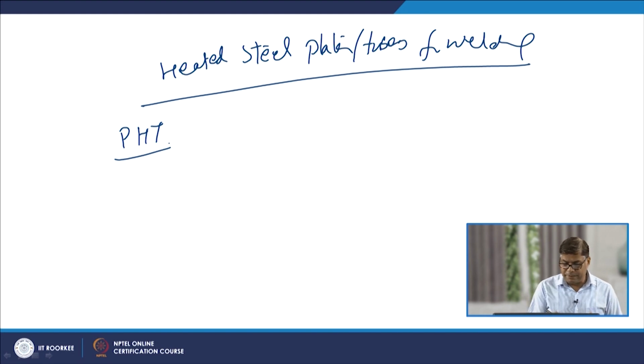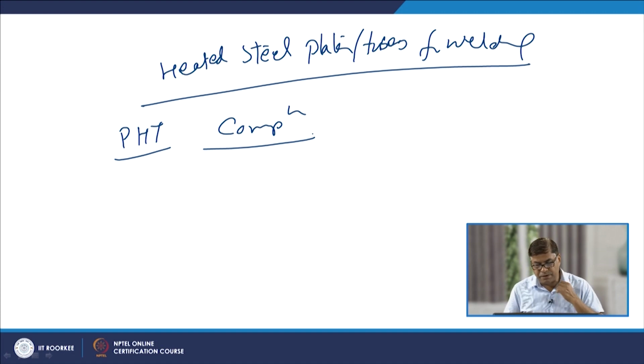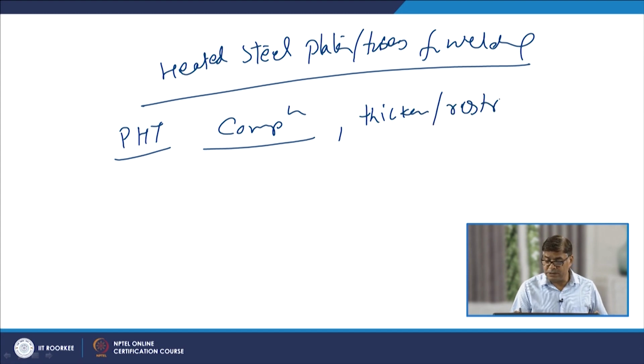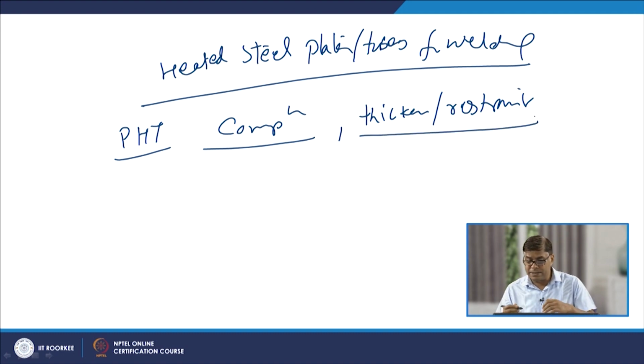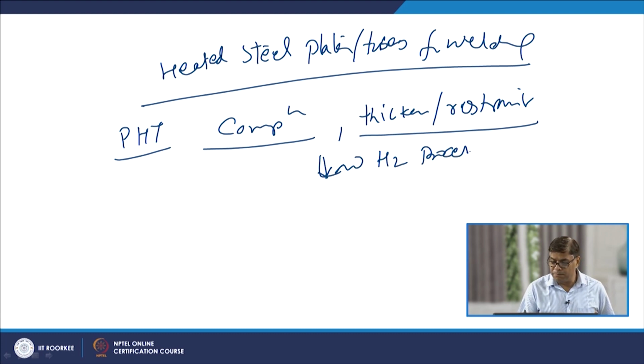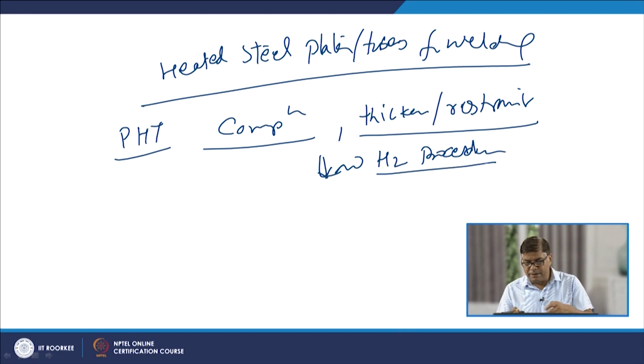While choosing the preheat temperature, certain points are kept in mind, like composition. A higher carbon equivalent in general goes with a higher preheat temperature. Then the thickness of the section or the restraint conditions under which the welding will be performed. Lower thicknesses and lesser restraint help us in reducing the preheat which can be used. Further, if we use a low hydrogen procedure, meaning the welding process is such that the hydrogen in the weld metal and the heat affected zone will be less, or the welding consumables are used and the cleaning of the surface of the plates is done in such a way that the possibility of incorporating hydrogen in the weld as well as the heat affected zone is reduced.